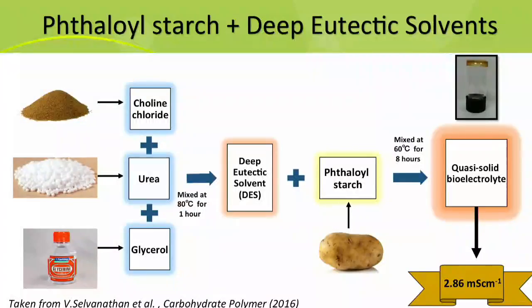Remember the 12 principles of green chemistry or chemical engineering? So we try to work towards those 12 principles. So what we do, we try to prepare natural deep eutectic solvent. So we use choline chloride, easily available in chicken feed. The urea, a lot, we use it in fertilizers, and glycerol. Join together, we get the deep eutectic solvent, add together with our modified starch, prepare the quasi-solid bioelectrolyte, and then test for its conductivity. We get a conductivity of 2.86 millisiemens per centimeter.